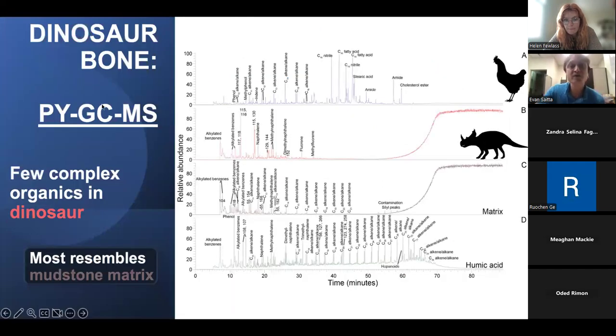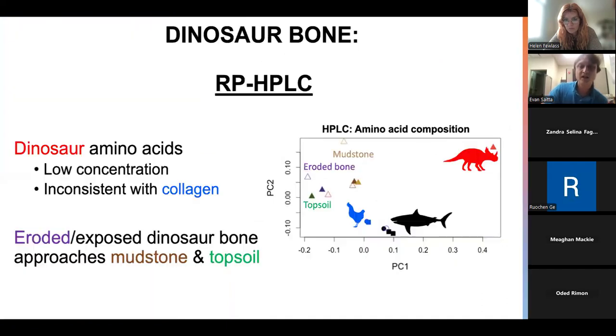If you examine these bones with pyrolysis GC-MS, you see that in the dinosaur bone here in red, there are few complex organics compared to the modern bone, indicating degradation of organics. And in fact, the dinosaur bone most closely resembles the pyrolysis fingerprint of the surrounding mudstone matrix. Not to mention the fact that sedimentary organics and soil organics, such as humic acids, can yield a variety of alkane-alkene products that were detected in the matrix. And so there's not a lot of evidence of intensive and high concentration organic material in these bones.